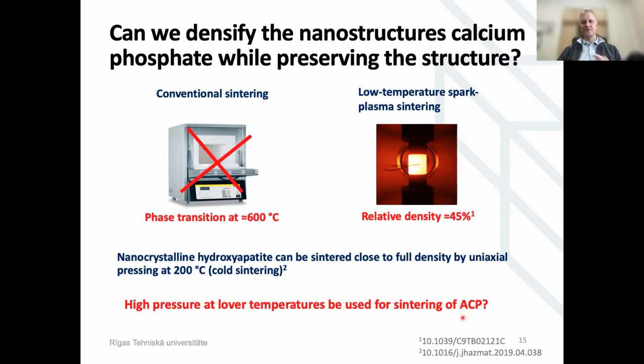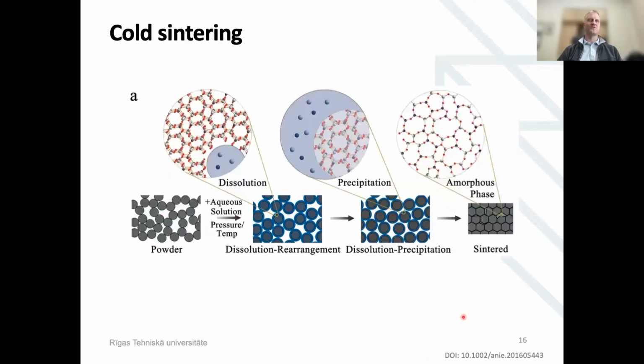Now, I just wanted to give you a little bit of an introduction of how cold sintering works, meaning that we have the nanoparticles, we have the powders, and we also add a little bit of liquid phase, which usually is water. And if we press strongly enough, the particles have connection points, and the water around the particles works as a medium, where the material from the particles dissolves and also precipitates back on the surface, in that way achieving the densification and formation of an amorphous phase on the border area.